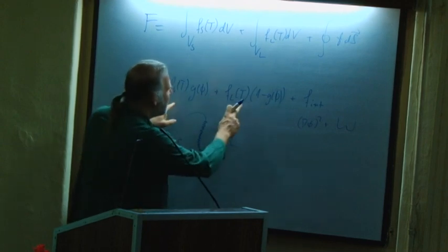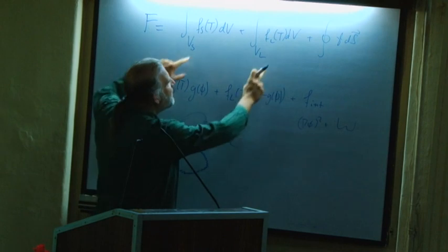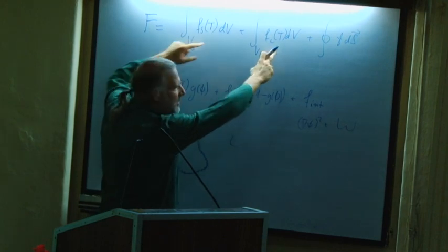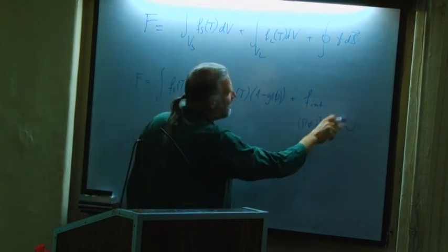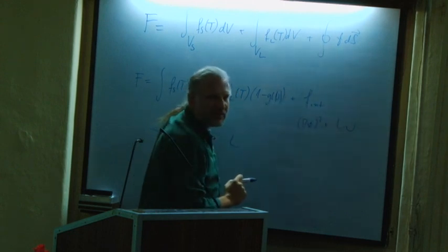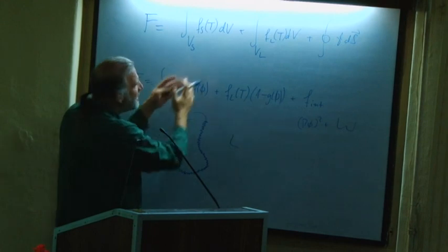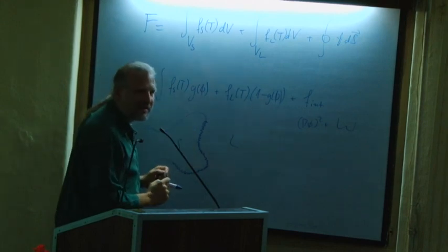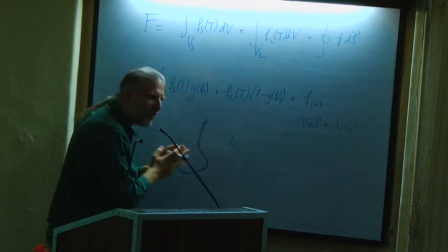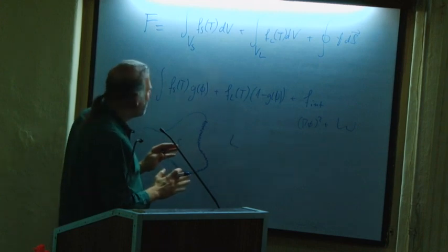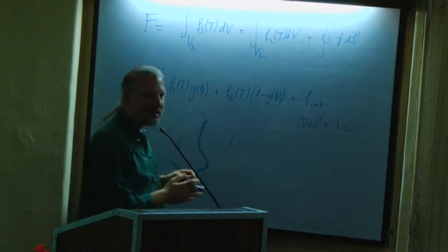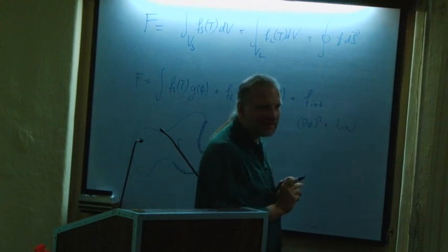And you see that these two terms are an approximation of the bulk free energy, and this term is an approximation of the surface energy. Okay? So in some sense, in this spirit, you can see the phase field representation just as a smoothing of the free boundary problem, where you replace a mathematical line by a profile that has a finite distance.